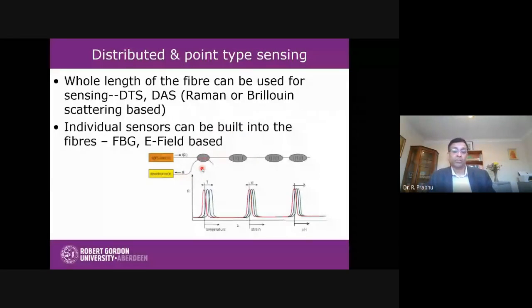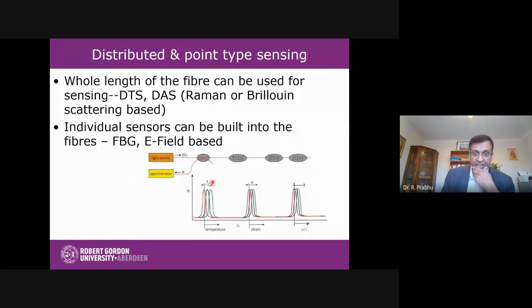Again, distributed sensing and point type sensing can be integrated. We were looking into this in our research here. The same fiber can be used for distributed sensing and for integrating additional sensors along the fiber. We can do multi-parameter sensing. In this case, you can use FBGs integrated in the fiber, monitoring temperature, strain, or pH for multi-parameter sensing. And this was in relation to oil and gas sensing.